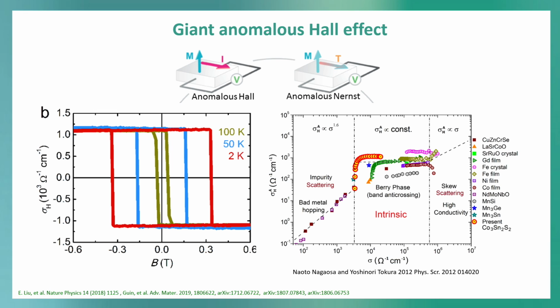magnetization perpendicular. And for the expert here, so Karplus, Tokura and Nagaosa, they have this very nice characterization of the anomalous Hall effect, where we can prove nowadays whether it's mainly driven intrinsically by topological properties, and this is indeed the case here in this material.